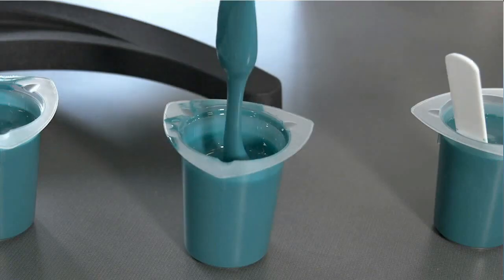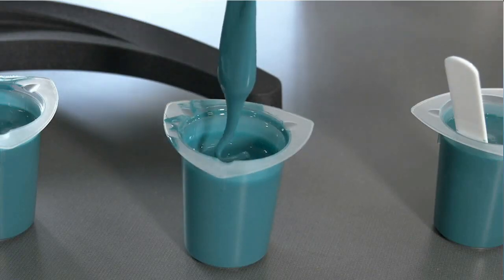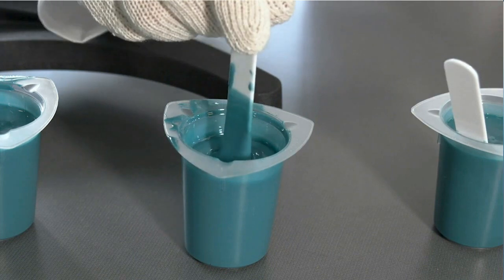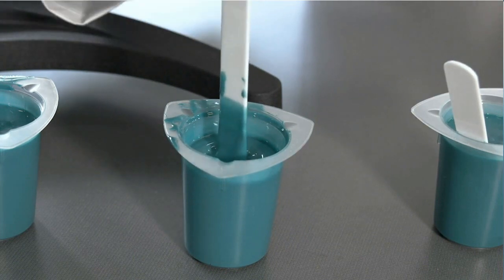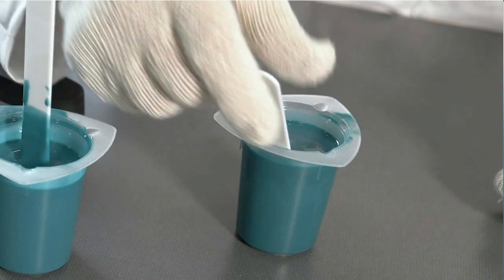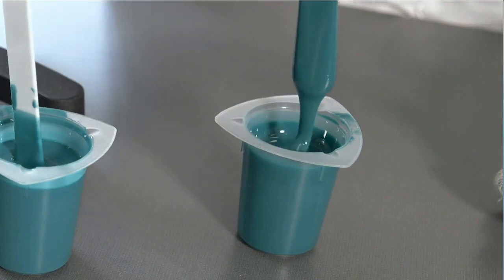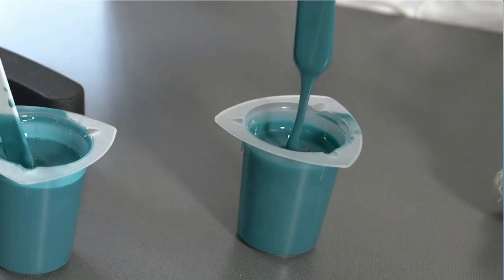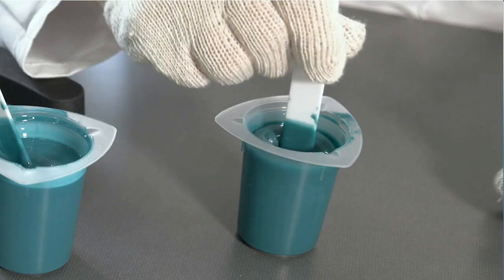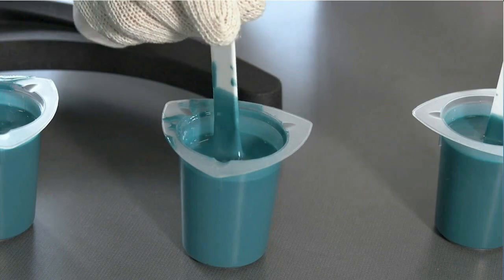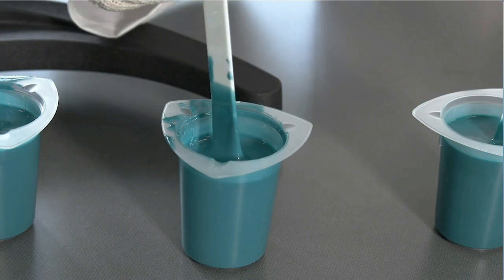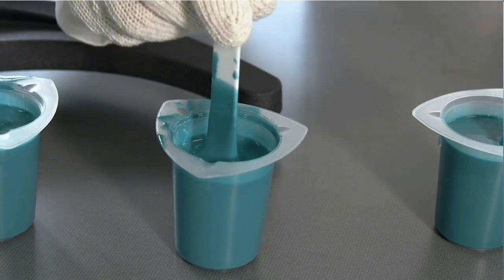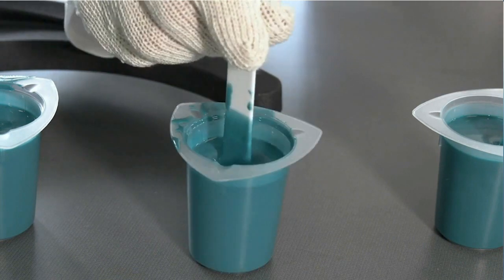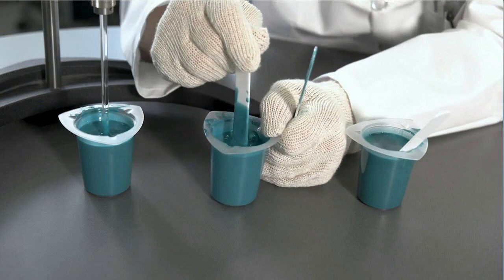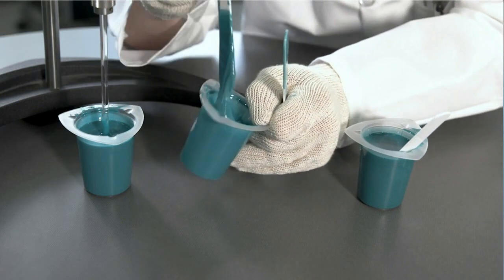So as you can see, the viscosity is really building past the point of flow, and it's just about to gel. And typically, urethanes will gel in the center, so it's that center that will produce a little bit of a ball in there. You can see that much lower viscosity on this one over here. And this one's just about there. I can almost not pull the stick out without lifting the whole thing. So as you can see here, a very distinct gel of the material.